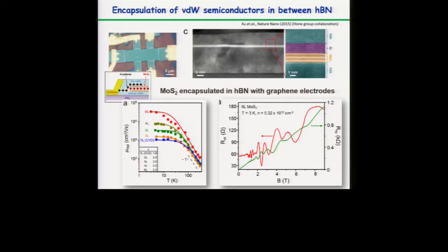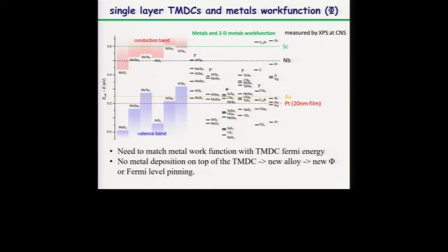Why? Because of the gap. The gap changes with thickness. The thinner it goes, in the single layer limit, the gap is larger, around 2 electron volts. And then there is another problem, the alignment. We need to align either the conduction or the valence band to one of the metals. This is some of the work function of metals, and we need to align them to either the conduction or the valence band. So it looks simple: we can just choose a low work function metal, align it with MoS2, and then we will get a good contact.